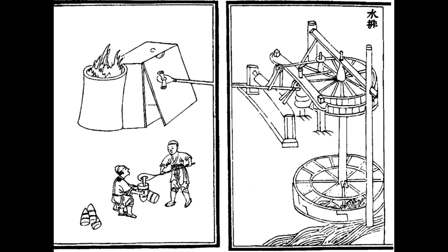We start to see these as early as the 13th century AD in Europe, involving breaking cast iron into smaller chunks and then heating these in an oxidizing environment so that the iron would melt and excess carbon in the form of graphite would burn out, leaving a bloom below where the iron had been. That technology had matured enough to produce armor and weapons-grade steel by the 15th century, which is, to be clear, quite a bit later than the 1st century BC, when the method was mature in China.